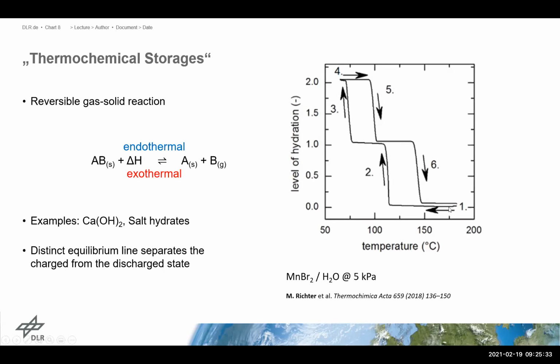So the theory from the last slide, one distinct line, is now that we have 2 lines, for the first mole and the second mole of water, and we have, of course, a hysteresis here, which makes this material not that attractive for thermochemical energy storage, but it proves that we have these distinct lines.